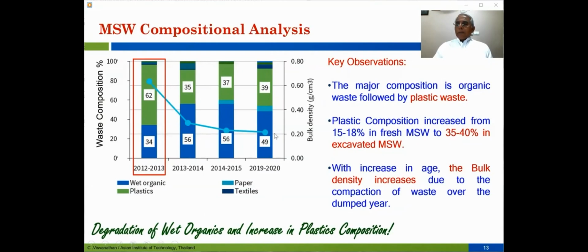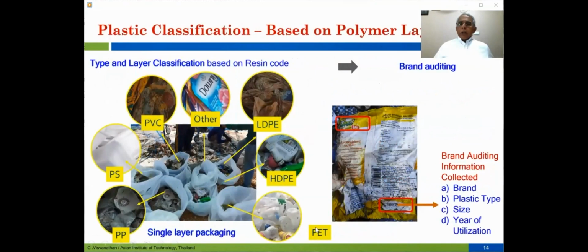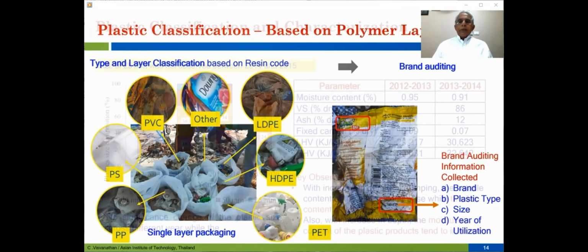That tells the organic biodegradable fraction is degraded, the wet organic degrades, and because of that there's an increase in plastic composition. Here we also looked at the plastic classification based on the different polymer layers. Okay, and we also looked at different types of plastics, starting with polypropylene, PS, and PVC, etc. All the 7 categories. And we also tried to identify which brand contributes the major plastic in the dump site. So it gives you some analysis, and brand auditing also begins.